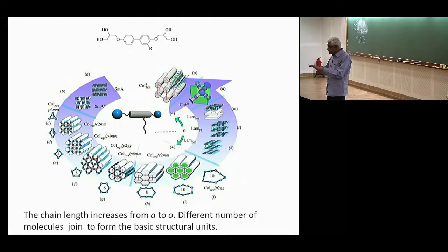It's a fairly complex elastic response, obviously, because you have the elasticity of what is called the C vector. The projection of this tilt in the plane of the layer is called the C vector. And it is a polar vector, by the way, because if I project this way, it's oriented that way. If I project the other way, it's oriented the other way. And so the curvature distortion of the C vector field is one thing.